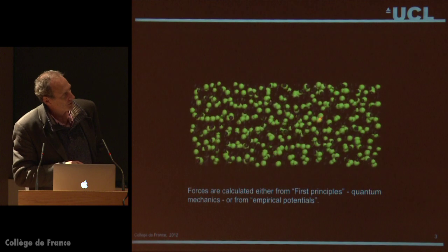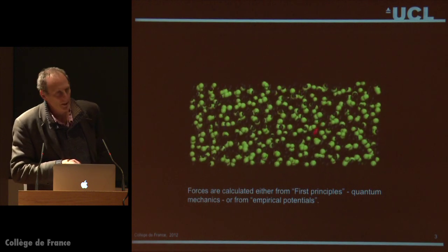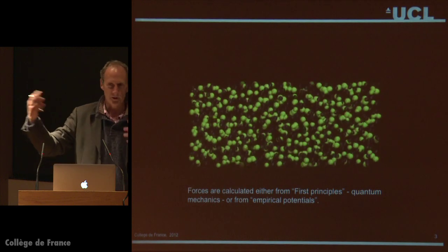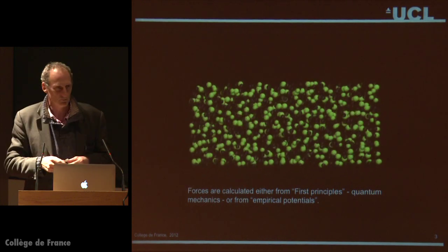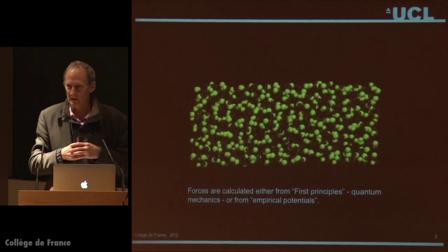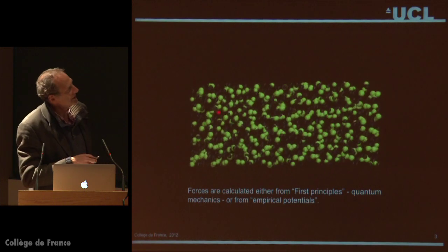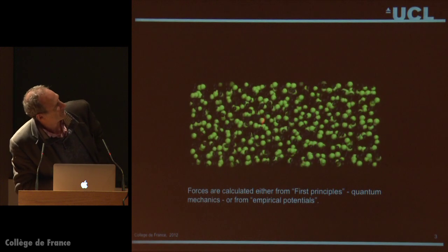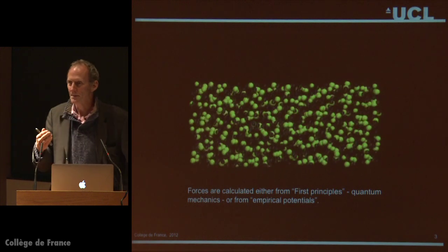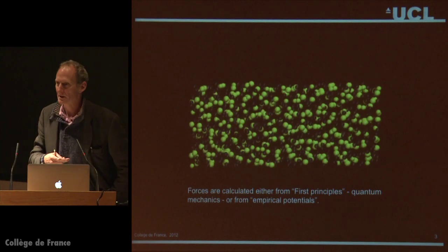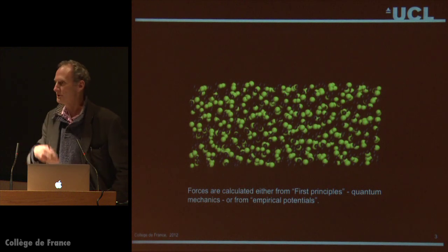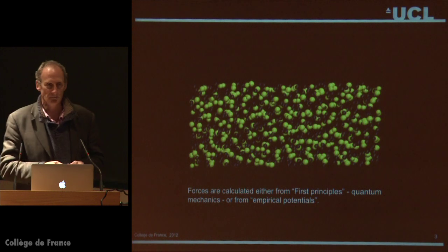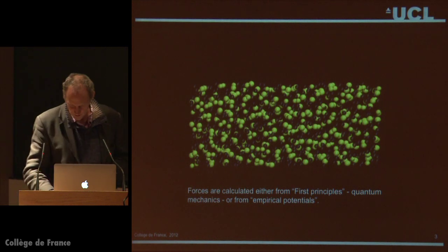But it tells you a couple of things. One is that if you follow atoms in the melt part, they diffuse, they just move through the melt, and just by following them and calculating their root mean displacement, you can calculate the diffusion coefficient directly. In the solid part, which is now gradually disappearing, there is no diffusion, because on the timescale of these simulations, jumps are so infrequent that you can't calculate them in this direct manner, and we have to take a slightly more fiddly approach.